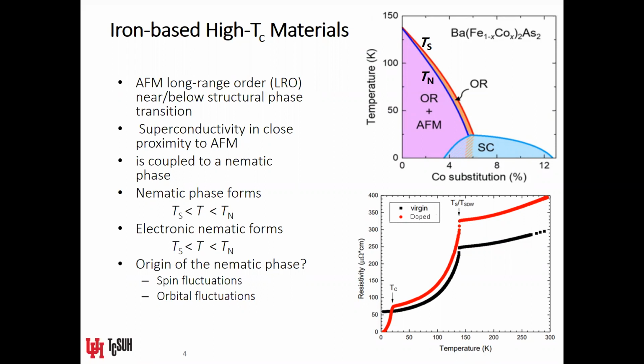And you see those phase boundaries labeled. In the non-superconducting phase, or in the normal state, the crystal symmetry is tetragonal. As you lower the temperature, you enter an orthorhombic phase, and you start to enter a magnetically ordered phase, that's the antiferromagnetism. Okay, so as you dope this material, and we're showing the doping along the horizontal axis, you can then drive down the structural phase transition temperature and the magnetic phase transition temperature.